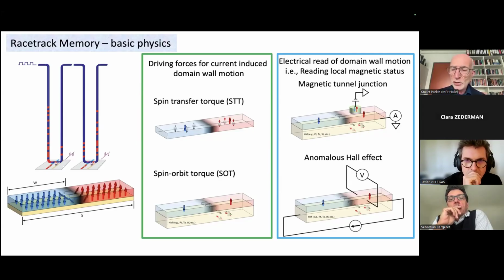On the right-hand side, you can see at the top, we could integrate in principle a tunneling junction into the racetrack. So the racetrack now is one of the magnetic electrodes. Then there will be an insulating layer, typically magnesium oxide, and on top would be a counter electrode, shown here in this greenish color. That counter electrode would typically be fixed in its magnetic moment direction, and as the domains move underneath, the magnetic moments in the domains would be either parallel or anti-parallel to the fixed moment of that counter electrode in that tunnel junction, and then they can be detected very efficiently with huge signals in this way.